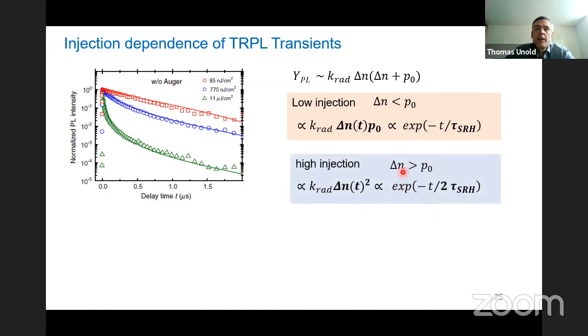If you go in high injection now, so your delta N, your photoexcited carrier density, is larger than the background doping, then you are proportional to delta N square. And that leads, in the Shockley-Read-Hall dominated case, to a decay that's going with two times the lifetime. I wrote this wrong. This has to be up here. So half the lifetime. So just imagine the two is on top of the denominator. What this means is that your lifetime, if you measure at very low injection, is mono exponential.